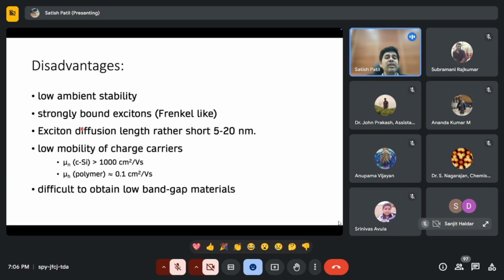The diffusion length: an exciton is a neutral particle, and the diffusion lengths are very short, 5 to 20 nanometers. That limits the thickness of the solar cells. You cannot make very thick solar cells using this material. Charge carrier mobilities of these materials are also very low.